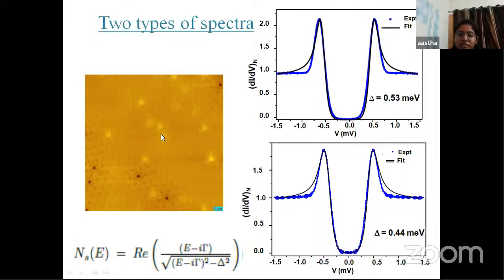These are the defects that were already reported in PdTe2. Upon intercalation, what is new are these dark spots surrounded by a well-defined interference pattern. We did spectroscopy at different locations, near the copper intercalates and away from the copper intercalates, and we mainly observed these two kinds of spectra.